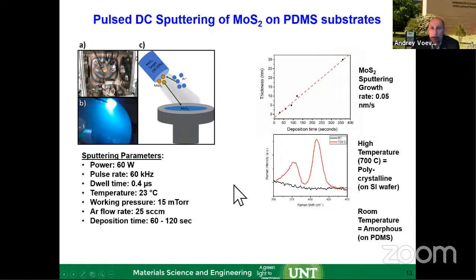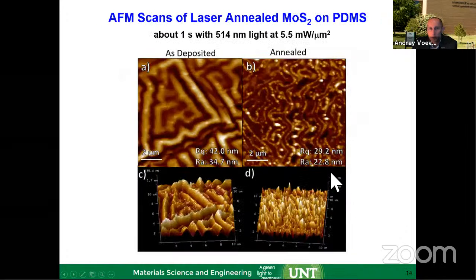And once you produce it, it's amorphous. That means if you shine the Raman laser on that, you will have the black curve, no peaks, no in-plane and out-of-plane vibrations, because there is no crystallinity. And only after laser annealing do you form the hexagonal materials, and you start seeing the peaks appearing in here.